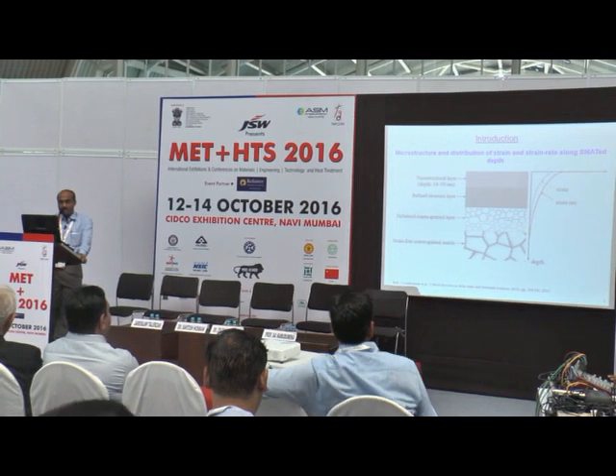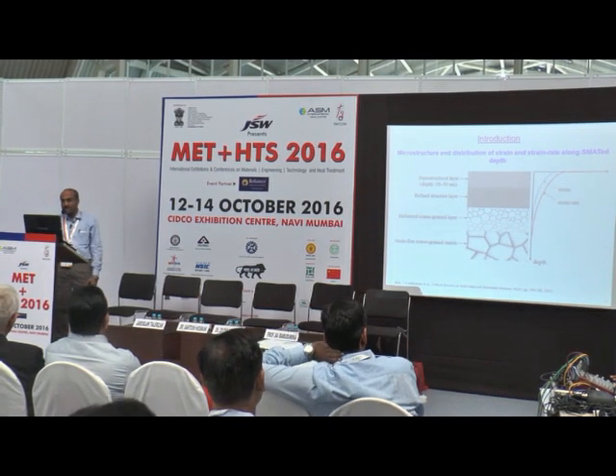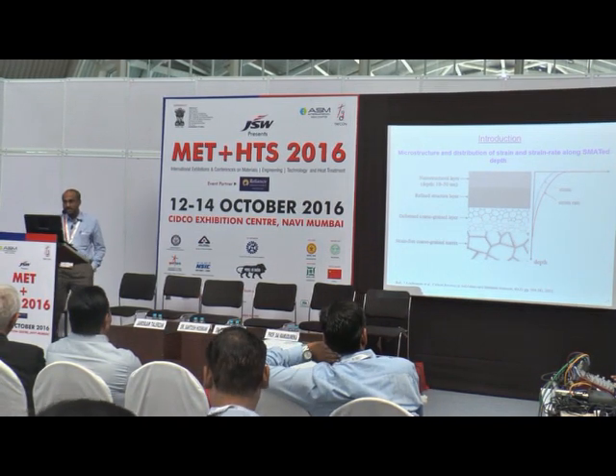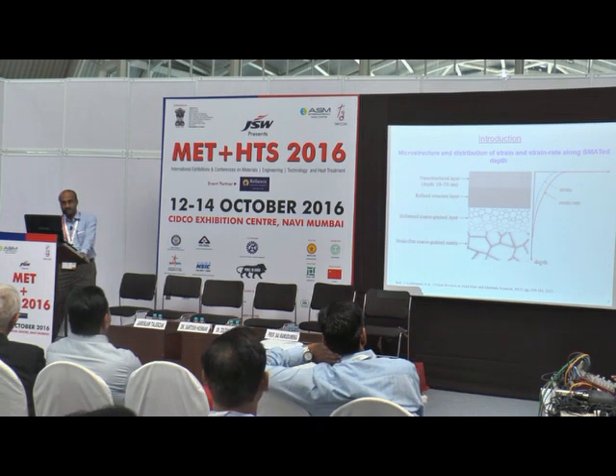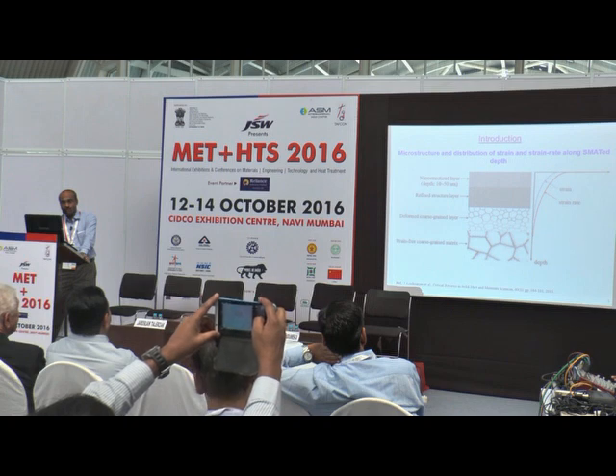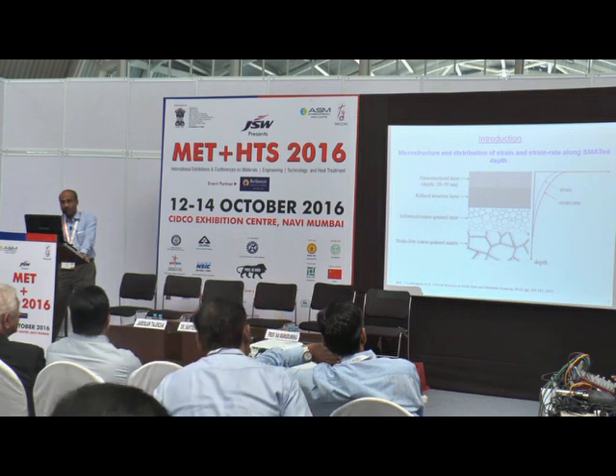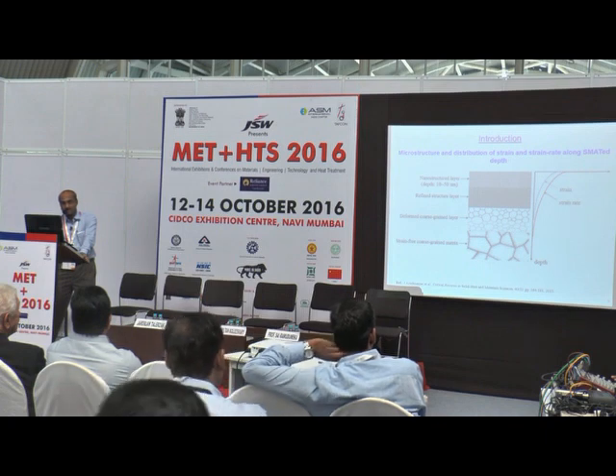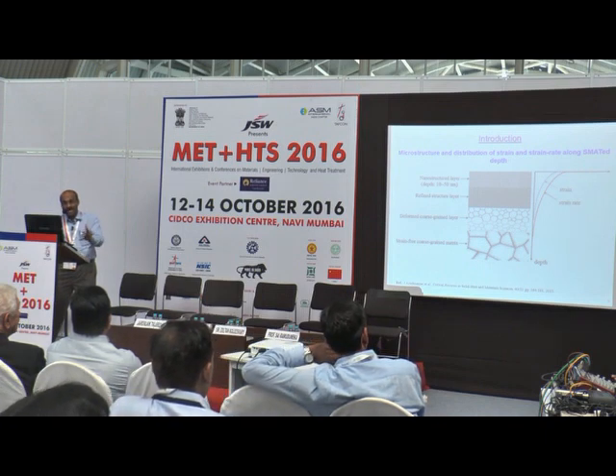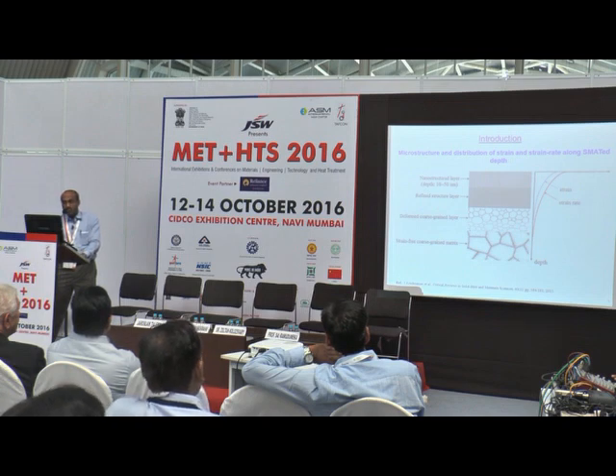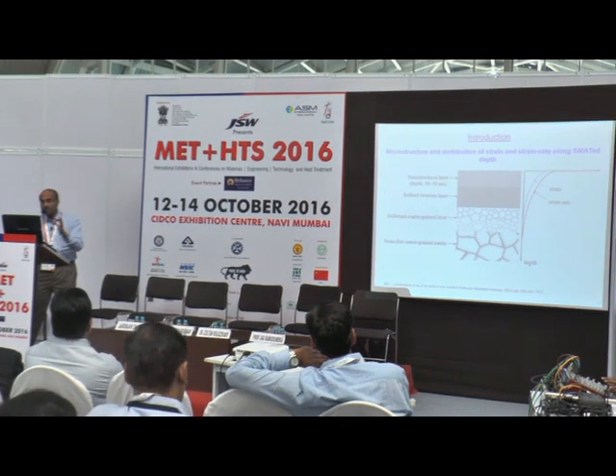What is happening in the case of SMAT? You have accumulation of strain at the specimen surface, and that strain gradually decreases as you move inside the specimen. That means you have continuous deformation, and due to this deformation, you have the formation of nanograins at the specimen surface. These nanograins or crystallites help us in various ways. What I'm going to focus on is how this nanograin formation affects the nitriding behavior.